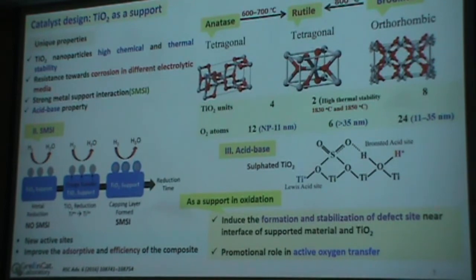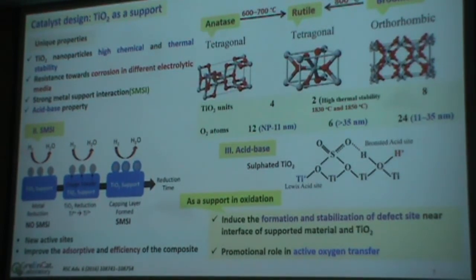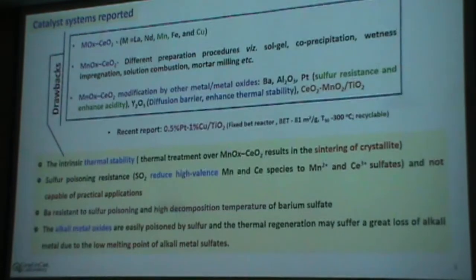Further, especially for the oxidation reaction, it induces the formation and stabilization of defect site near the interface of the support material and the TiO2, and it plays a promotional role in the mobility of active oxygen species, because mobility is very important in the oxidation reaction. Based on this, there are too many literatures on Mn-based catalysts, but those are mainly in combination with cerium because cerium has high oxygen storage capacity.